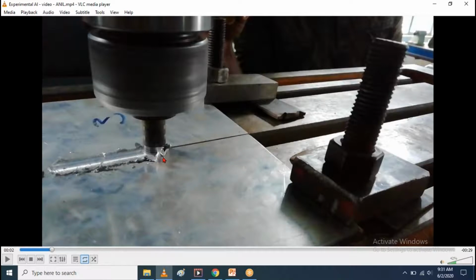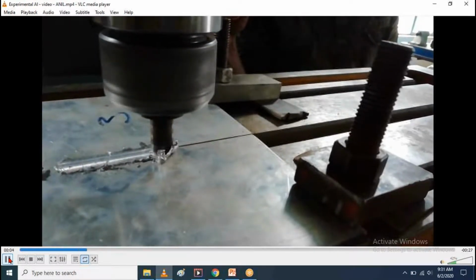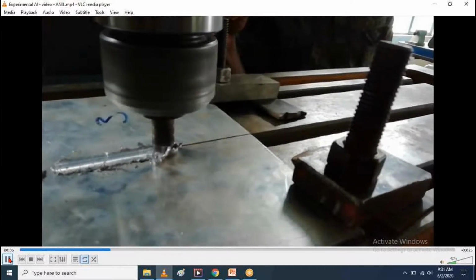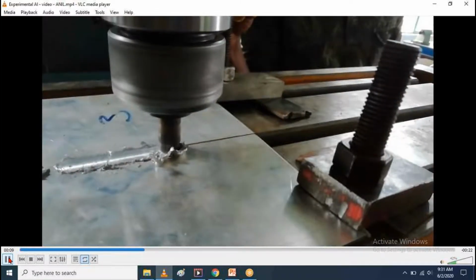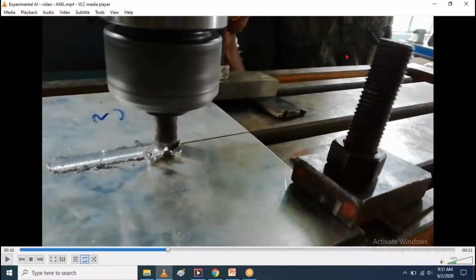These are very thin, less than 1 millimeter thick material, like an aluminum flake. It is coming, and this is how one can do a friction stir welding process on a simple vertical milling machine.